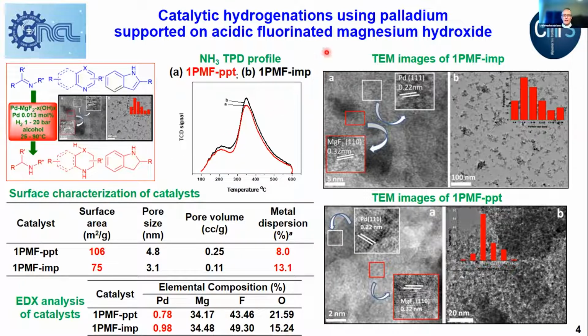and typically these fluorinated magnesium hydroxide supports were clearly acidic according to the ammonia temperature-programmed desorption profiles of catalysts prepared by precipitation or impregnation, as shown here. And further characterizations regarding the surface of the catalyst highlight that the precipitated catalyst had a higher surface area by comparison to impregnated catalyst, but the impregnated catalyst had a better metal dispersion.